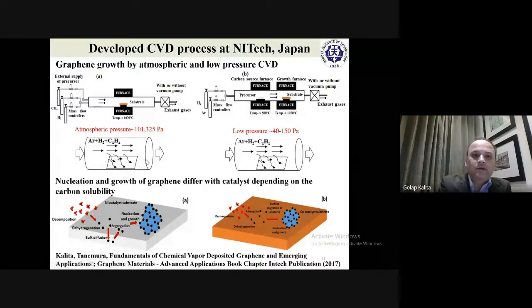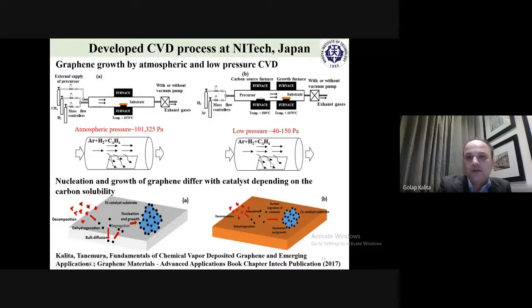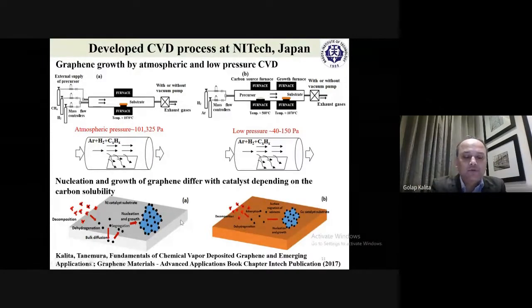By this, we can control the flow of gas and its interaction with the substrate. When gas flows, this is called laminar flow, and between this laminar flow of gas and the substrate, there is interaction with the substrate surface, where nucleation of graphene as well as HBN domains occurs, and it grows as a single layer on the surface. Depending on the metal catalyst, you can also have various growth mechanisms. Like in nickel, you can have diffusion of carbon, then segregation to the surface, whereas on copper, dehydrogenation of the precursor, then nucleation and growth occurs.